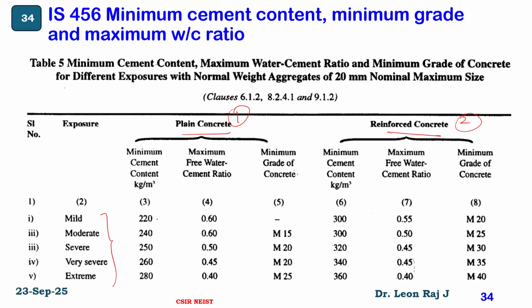For plain concrete, the minimum cement content increases from 220 to 280. But the maximum free water cement ratio decreases from 0.6 to 0.40, and the minimum grade of concrete increases from M15 to M25. At the same time, for reinforced concrete, the grade of concrete increases from M20 to M40. In extreme conditions like coastal areas, you have to go for minimum M40 grade of concrete, the cement content is minimum 360 kilogram per meter cube, and the maximum water cement ratio is 0.40. So it is decreasing from 0.55 to 0.40.